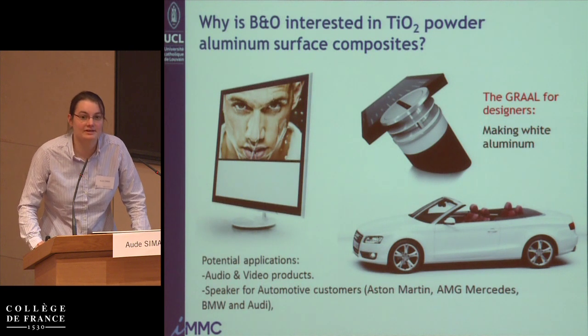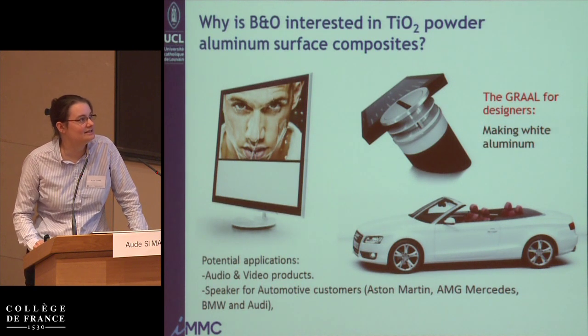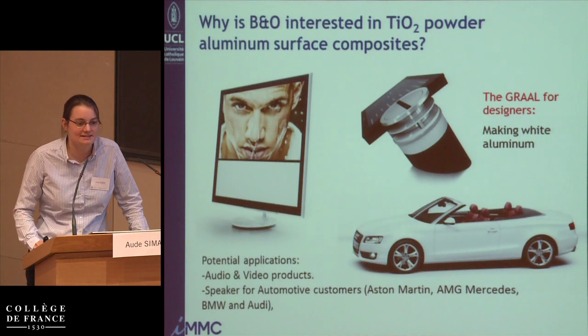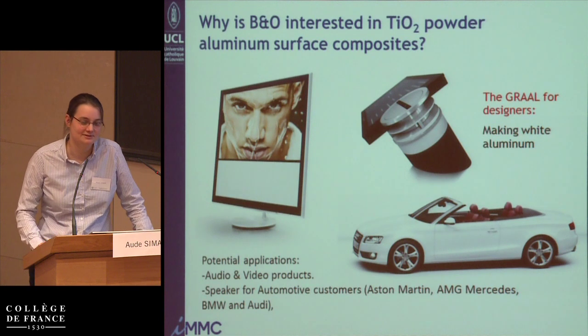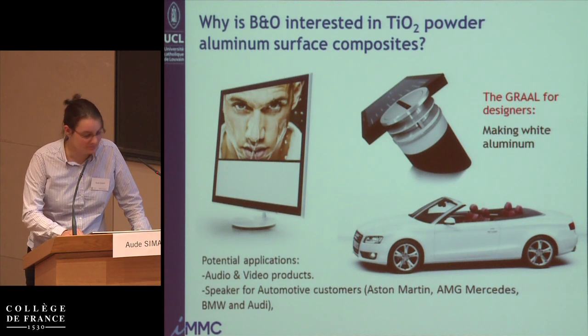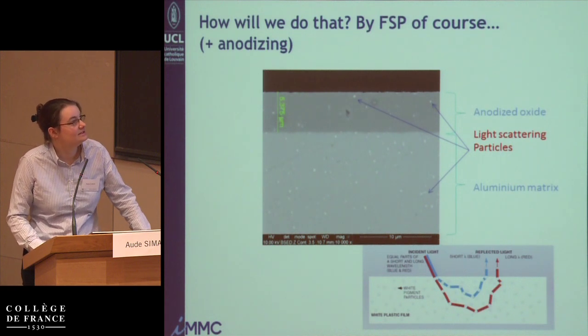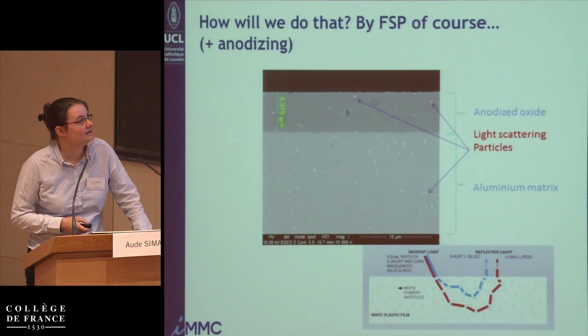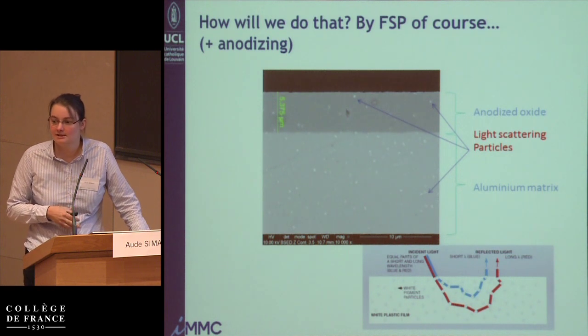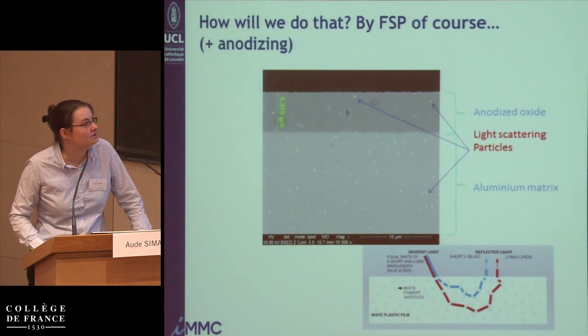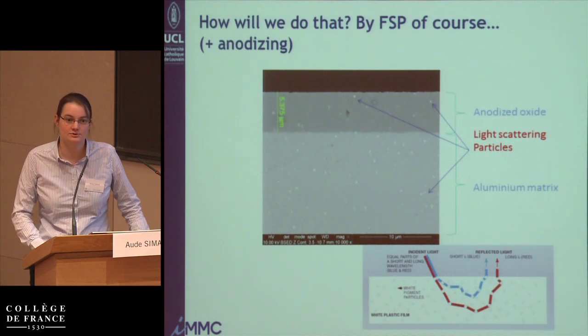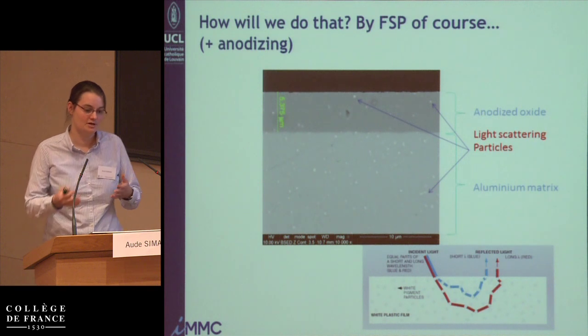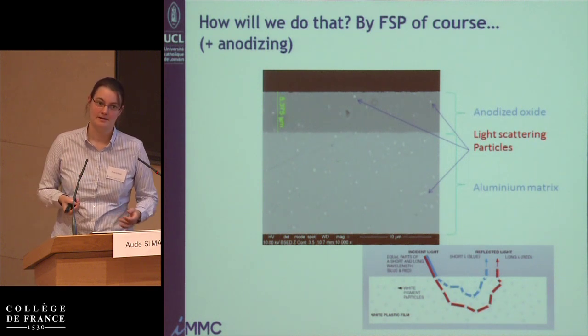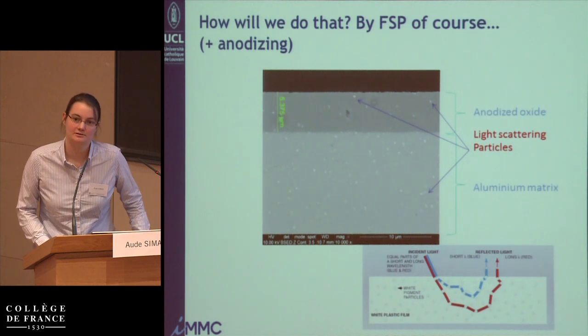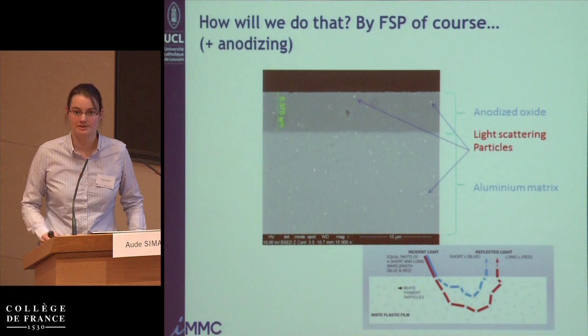The grail for designers is actually getting white aluminum, because aluminum is design, and white aluminum sounds really the top of design. So what they wanted to do is insert titanium oxide in an aluminum alloy, and use the light scattering effect of the titanium oxide to give a white appearance to the surface. If you have a lot of the light that is reflected, and that will be improved by the titanium oxide, well, that would have a white appearance instead of a gray appearance.